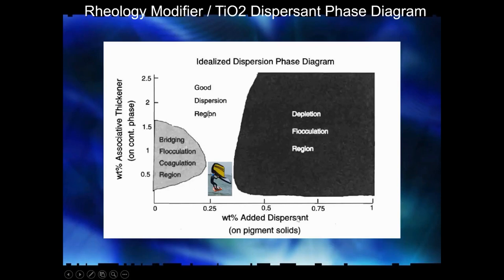So if you add too much dispersant with your pigment, let's say you have clay, calcium carbonate, you have all sorts of other mined minerals, and you just throw it into one batch and you say, okay, I'm going to add 1% surfactant. Now, what happens? As you add your rheology modifier in there, you go into the depletion flocculation zone. This black zone is what we call a big boulder. You don't want to hit it. On the other side of the thing is, if you don't have enough dispersant to keep the polymers from sticking to your TiO2, you'll get a bridging flocculation. So there is a sweet spot, and you need to know where that sweet spot is.